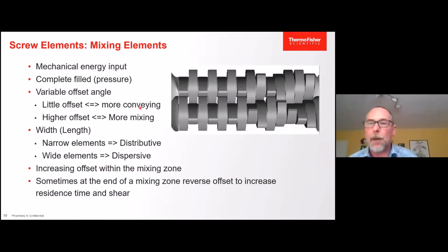Looking over to the next part is the screw element. Mixing elements can be arranged in various ways. So in a forwarding zone, in a neutral mixing zone, which will have higher mixing powers. Usually in those zones, we achieve the highest energy input. So the material temperature will increase. The pressure will be high, so the mixing zone always will be full. There will be always pressure inside this mixing zone.